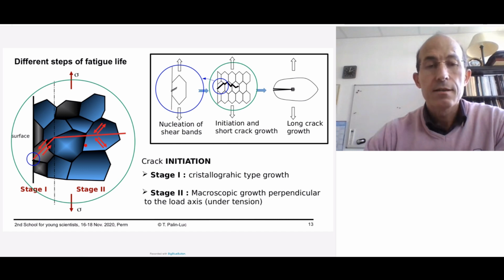And when this crack is long enough compared to the characteristic size of the microstructure, or the grain size, meaning when the crack has a length of approximately 5 grains, the crack bifurcates and begins to grow perpendicular to the principal stress. So we are in the case of long crack growth. It is important to understand that crack initiation is governed by the crystallography and by shear. And when the crack is long enough, the crack propagation is governed by the macroscopic principal stress, that is the opening stress.